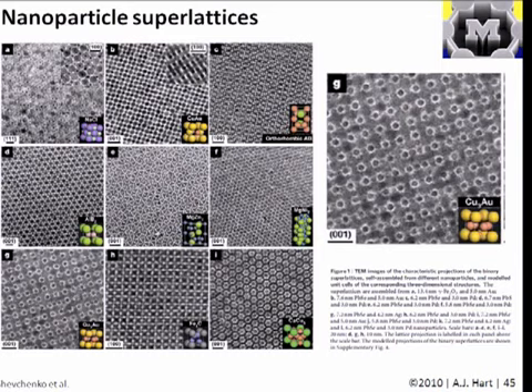And another very important consideration that hasn't been shown in any of these results is that the monodispersity of the particles you start with is very important. It's been shown by experiment and simulation that the standard deviation in diameter needs to be about 5% or less to get good packing of these structures. So the ability to synthesize very monodispersed nanoparticles is essential to get this type of packing. And for example, if you can't make a certain material monodispersed within a certain size range, you pretty much can't achieve this degree of packing as shown here.